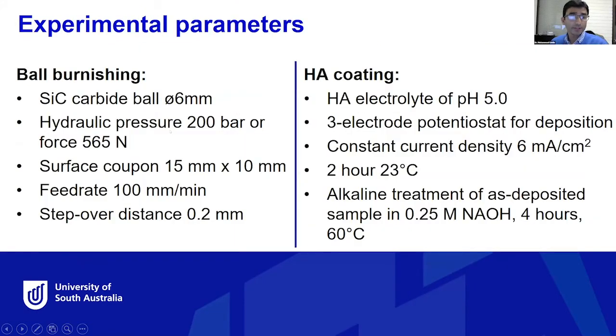So, some of the parameters involved in the ball burnishing and the HA coating. Ball burnishing we have done with a very hard silicon carbide ceramic ball, 6 millimeter in diameter, and we have used 200 bar of hydraulic pressure, which is equivalent to 565 Newton, a fairly reasonable force to apply to make some modification to the microstructure. The feed rate was 100 millimeter per minute, and 0.2 was the step over, which is the side step.